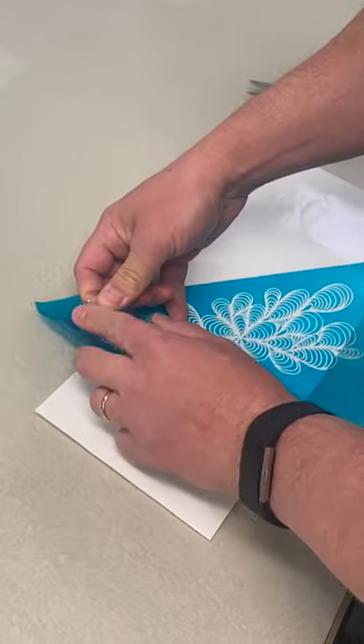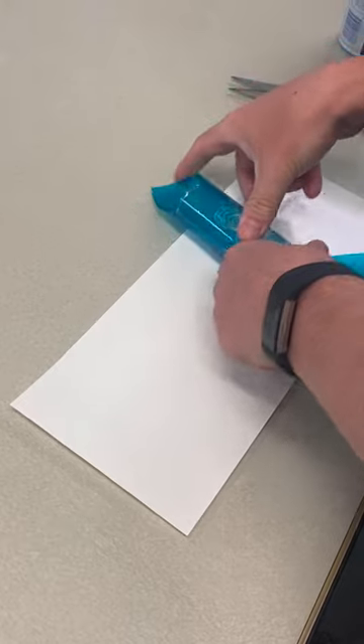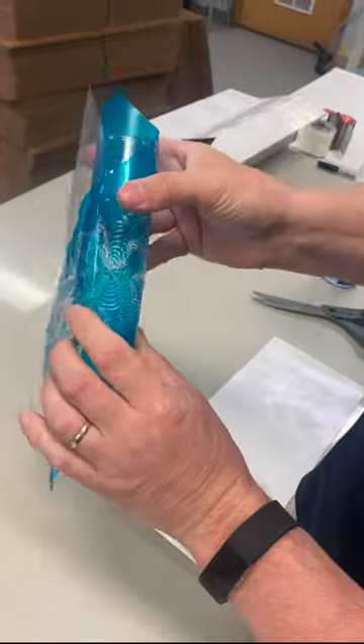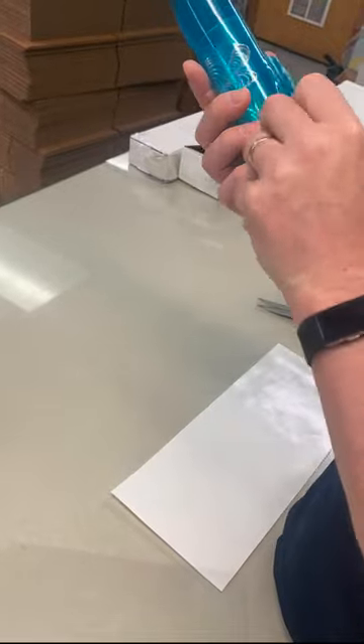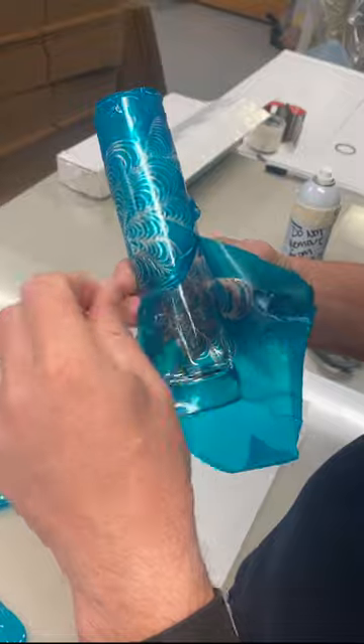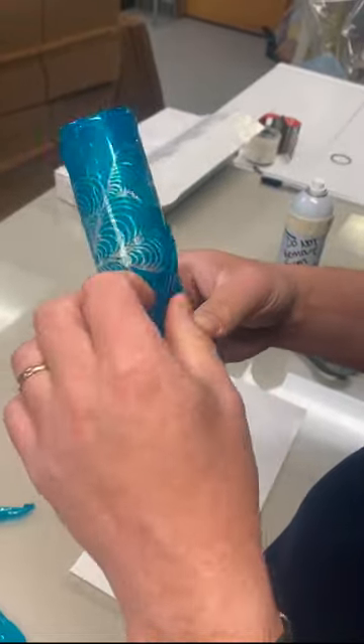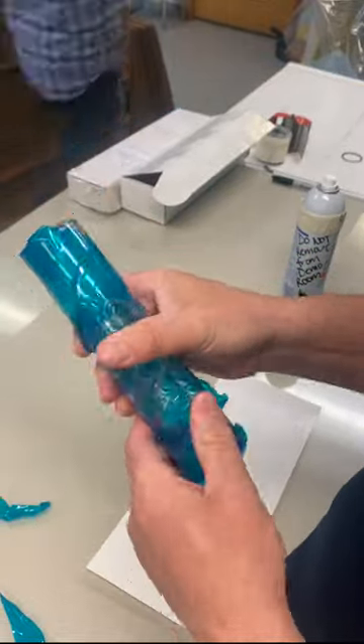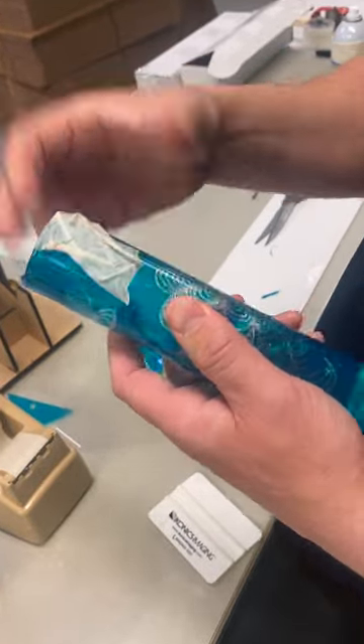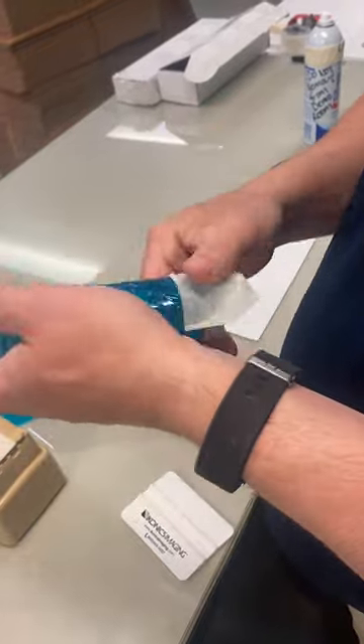R3 material is very pliable. It's got a carrier sheet to protect it, so it's easy to maneuver the glass across the image. What I'm doing here is rolling the glass since it's a cylinder shape across. At this point I'm just going to push on a little bit, give it a good adhesion between the glass and the resist, then pull out the carrier sheet once I'm fine with the look and design of where the glass and mask meet. Since the self-adhesive is going to attach itself to the glass, I'm just pushing down with my hands on the resist, removing any air pockets in the membrane and maneuvering the mask a little bit since it is a compound curve. Reposition the film as needed — very easy to work with. Depending on how the sheet of film aligns with my glass, I may have a few areas unprotected by photoresist, so in this case I use simple masking tape to fill in the gap so the abrasive doesn't etch the glass in those areas.